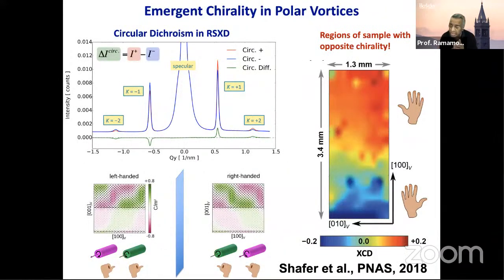The other interesting thing, and I will show you this again in a few minutes for a sister polar texture, is that if you look at these arrays of these vortices, they look like these tubes. And you know that it looks very much like a cigarette box. So if I come in with the right radiation, for example, soft X-rays, which have a wavelength of a few nanometers, I can have diffraction from them. And indeed, when you do this experiment, you can see that there is nice diffraction. That's a specular peak, but this is the -1 and this is the +1 diffraction peak.